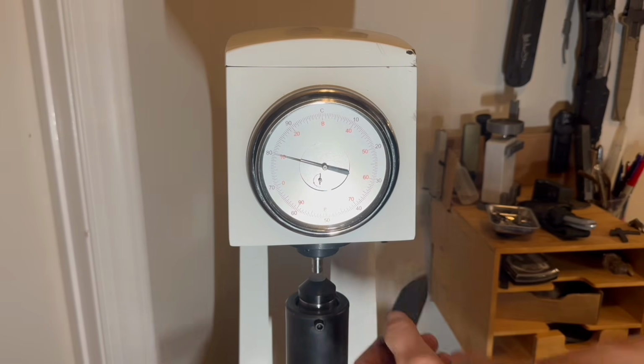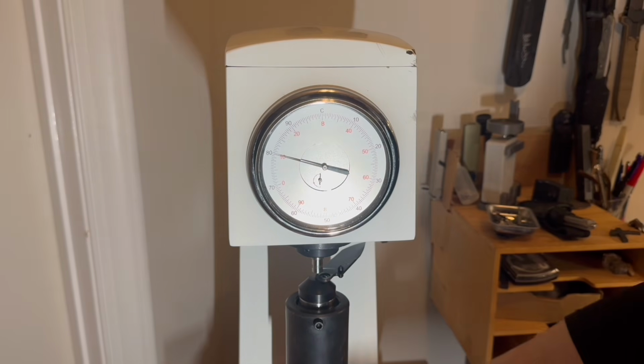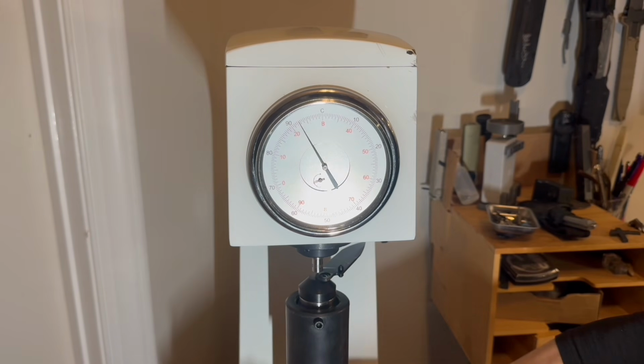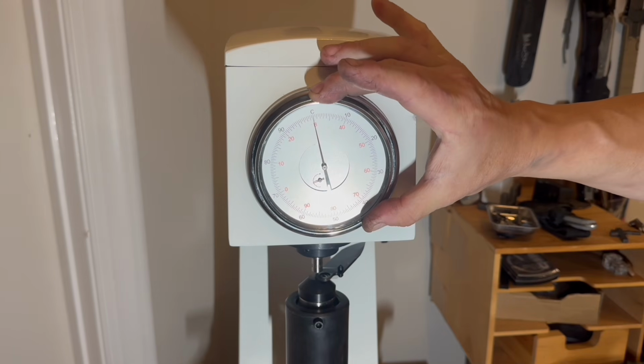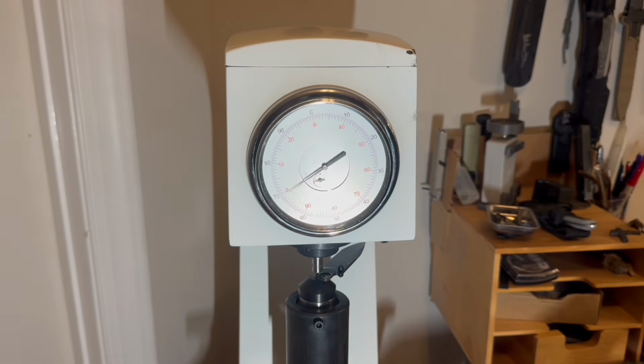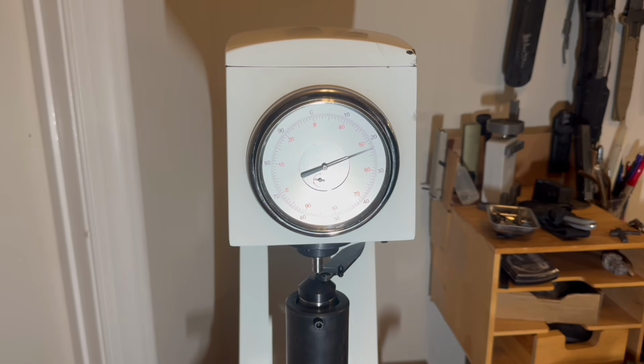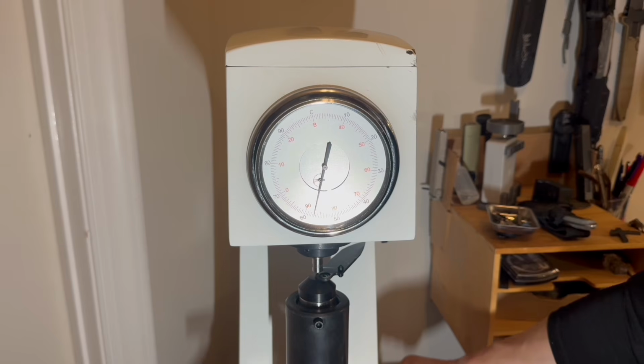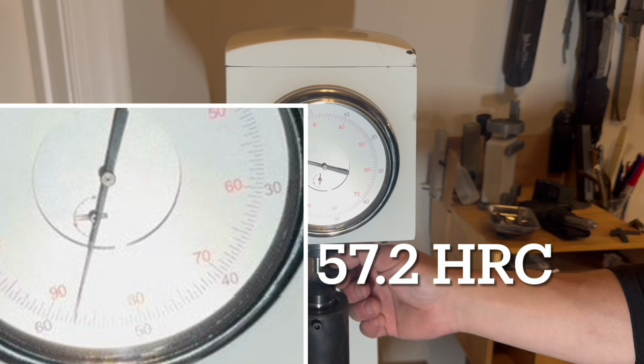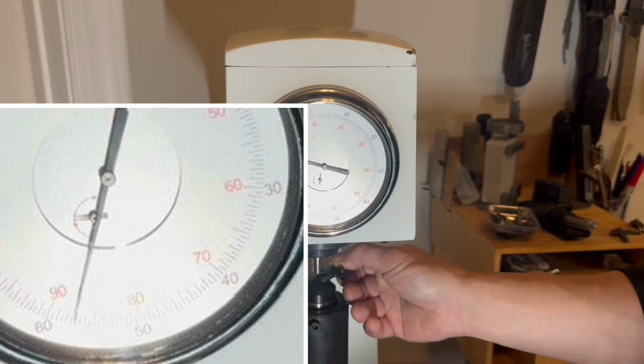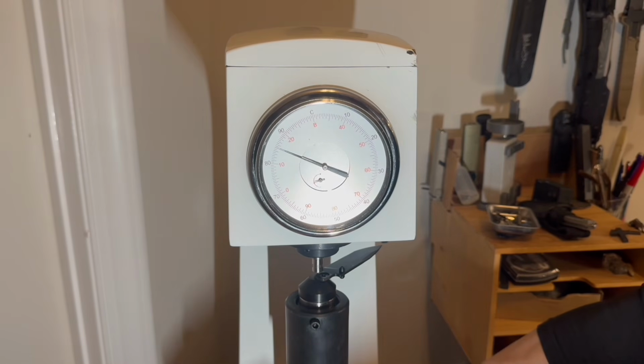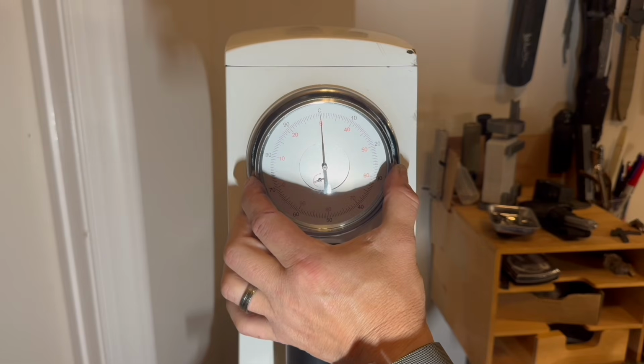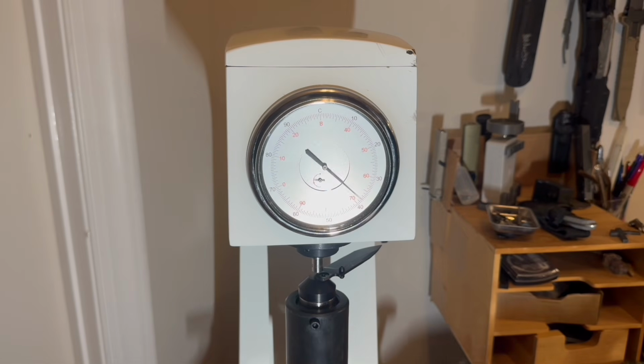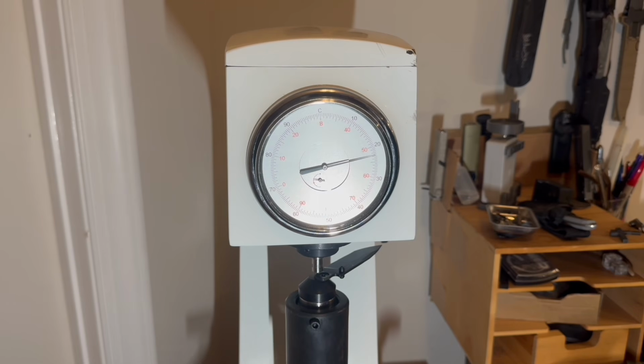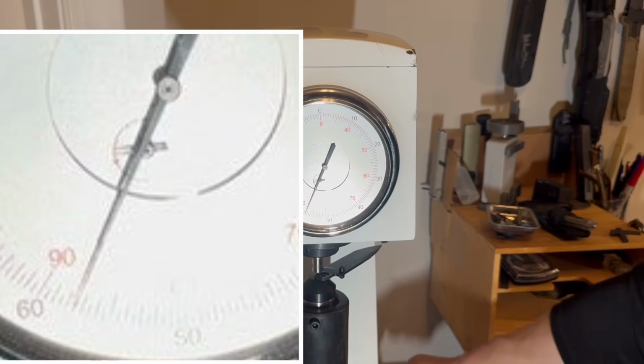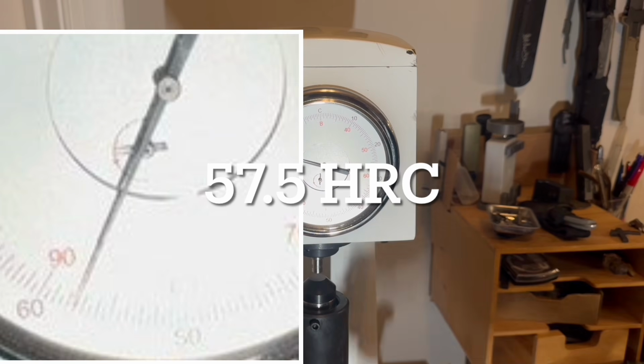I remove coating from one side because while I'm showing you this test, I'm also trying to answer the question that's been plaguing steel nerds forever. Does the presence of coating on the blade change the hardness test results? It's an interesting question, and there are different answers out there. Meanwhile, the first poke yields 57.2 HRC, which is on a bare minimum of recommended hardness by the steel's manufacturer. My working theory on the coatings is the coating itself doesn't change the result of the Rockwell tester. We got 57.5 this time.